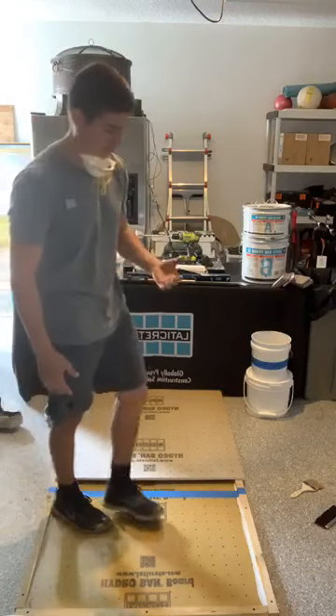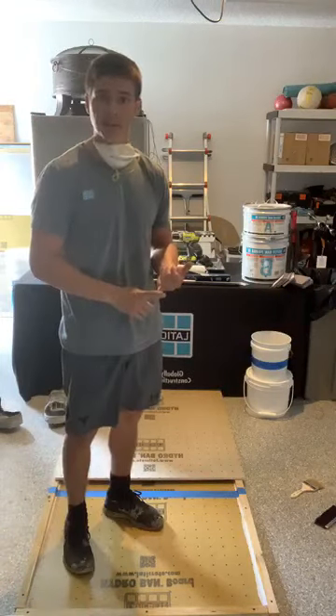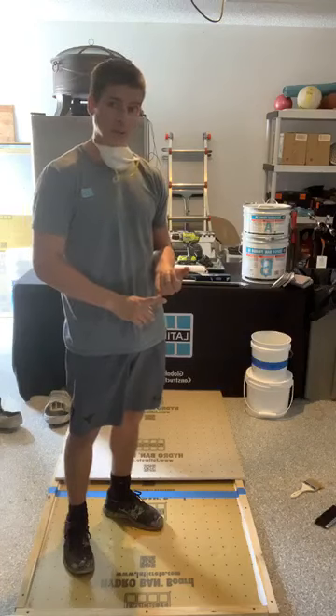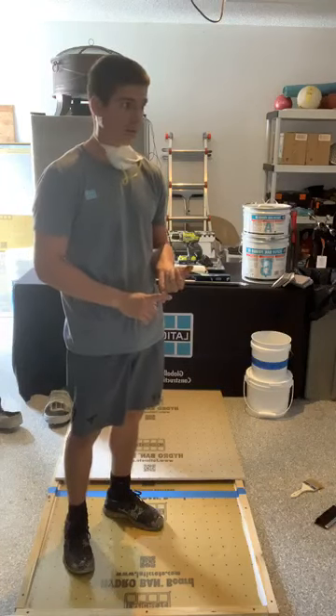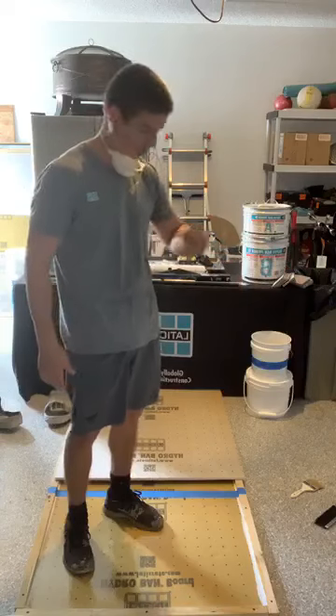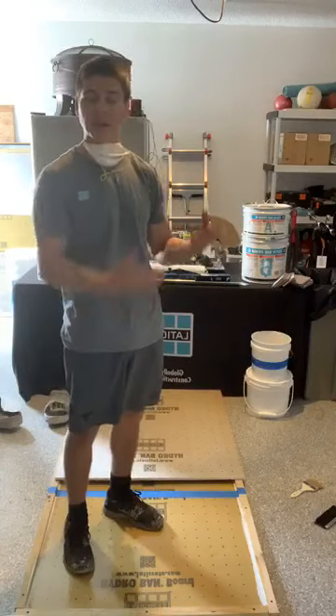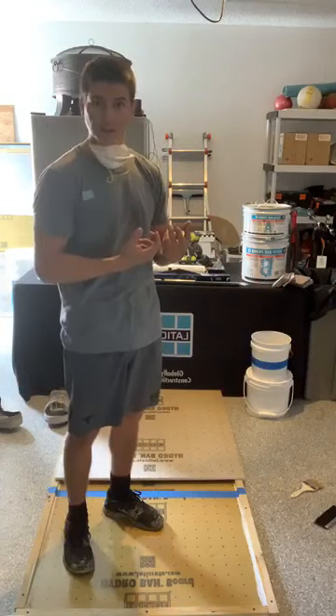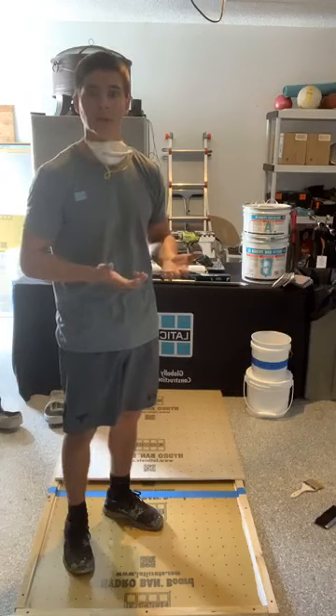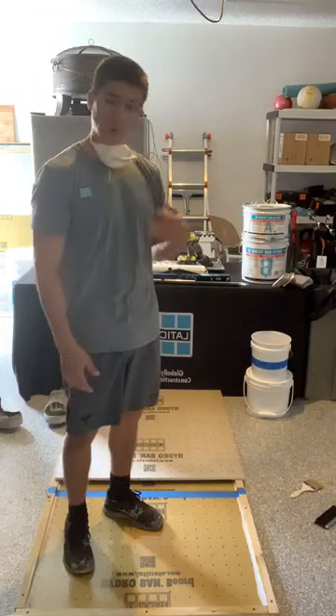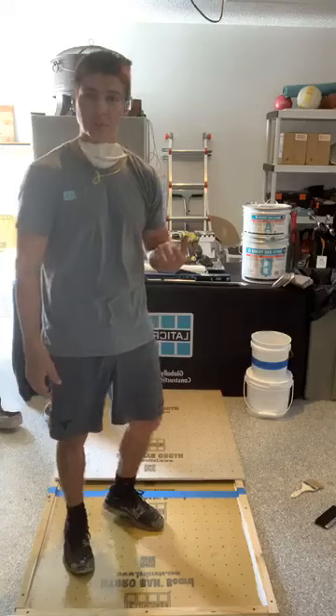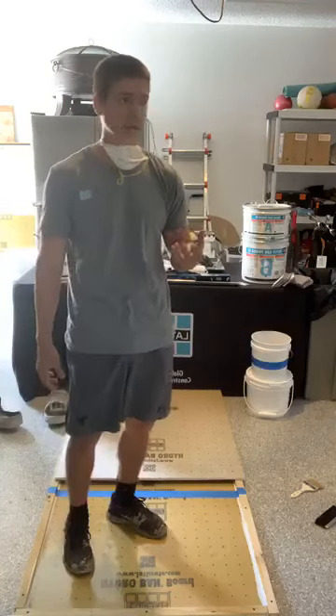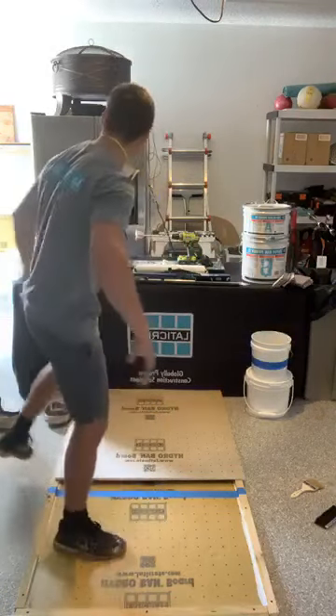You don't have to. Silica sand, one, it's very heavy. It's about 1 pound a square foot to get full coverage. I mean, you want to have no shine in this floor. You don't just sprinkle a little bit of sand, because if that absorbs into the epoxy, you still have a non-porous surface. So you're broadcasting to rejection, so your cementitious is actually bonding to that open sand, okay?